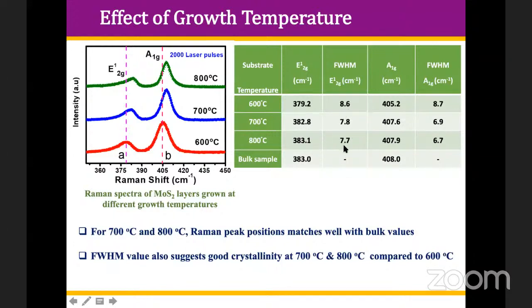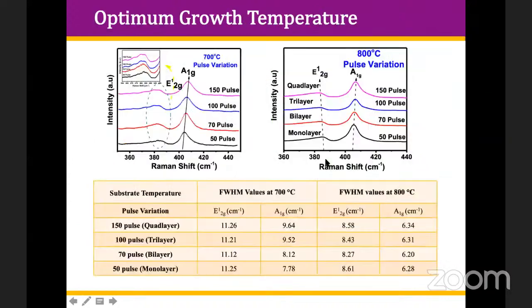And also you can see the full width at half maxima, which shows that these peaks are sharp, the crystallites, or you can say the grains, are larger. That means the better crystallinity of the MoS2 is there at 700 and 800 degrees Celsius. So we succeeded in making MoS2 by using the pulsed laser deposition technique, which is very difficult for large area deposition. In this case, we use a substrate of 1 centimeter by 1 centimeter.